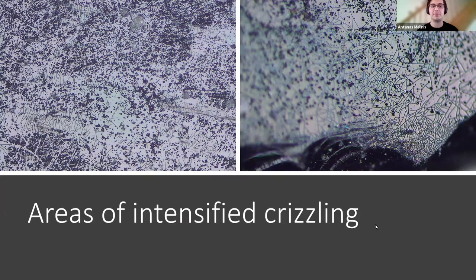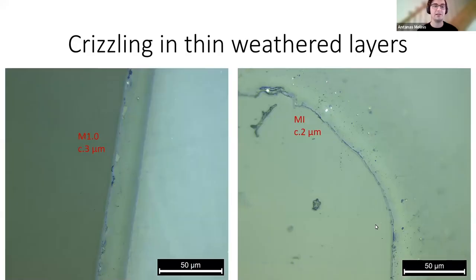It usually starts from edges or the points of physical stress, so radiating inwards. Other scholars like Steven Koob already drew attention to that crizzling can begin sooner where glasses were cut or ground. And even very thin hydrated layers can crizzle and flake off. Both of these pieces were exposed to the alkali solution for just 3 hours and developed a weathered layer just a few micrometers thick, which nonetheless crizzled within just a day.